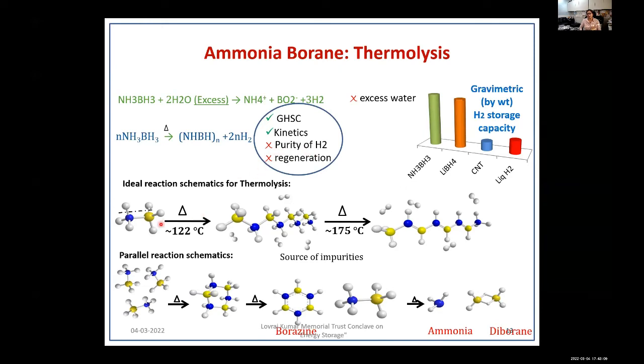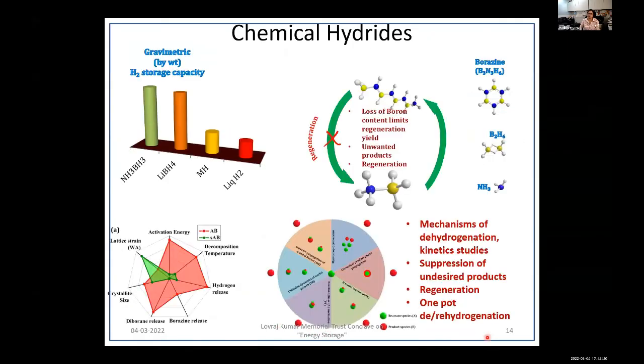These materials give hydrogen in steps. In the first step, 1 mole equivalent of hydrogen is released, in the second step the 2nd mole, and in the last step the 3rd mole, which takes place at a higher temperature. So why not take advantage of only the 2nd step and get 13 weight% hydrogen from this? Then we can also suppress the unwanted products which we are getting, like borazine, ammonia, and diborane, which could be poisonous for various other applications. That is what we have been doing in our lab. With different dopants, we were able to suppress the unwanted products to zero. Although the release of hydrogen decreased, with the different additives we were able to retain it.